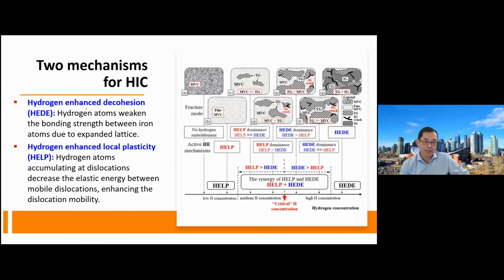The second one is hydrogen-enhanced localized plasticity, HELP. This mechanism means hydrogen atoms combine with the internal dislocations to make the dislocation mobility go up. If this mechanism applies, the steel usually becomes softer, and you can measure a decreased yield strength of the steel. If HELP applies, the cracking usually has ductile features. These two mechanisms are widely accepted and are applied to explain the HIC phenomenon.